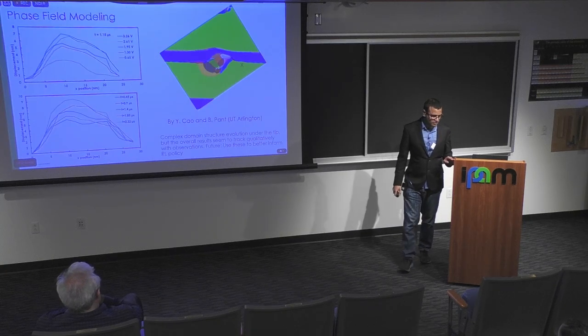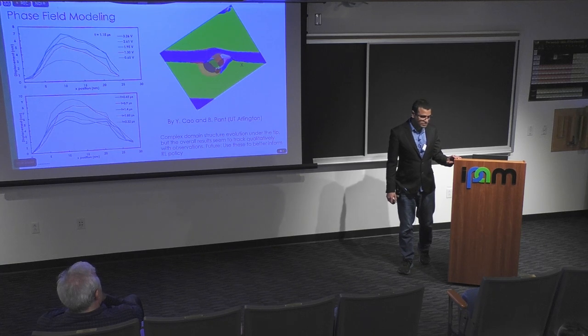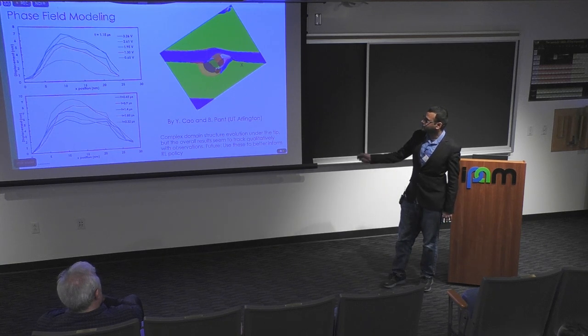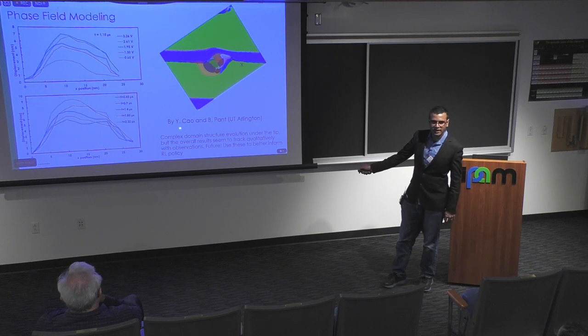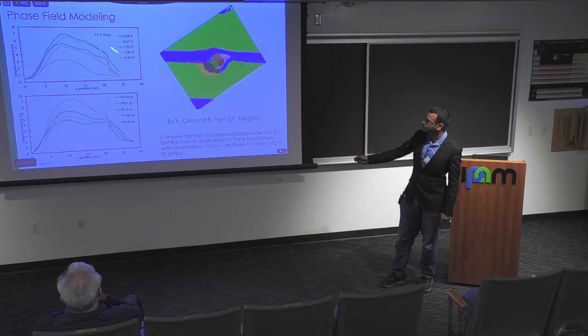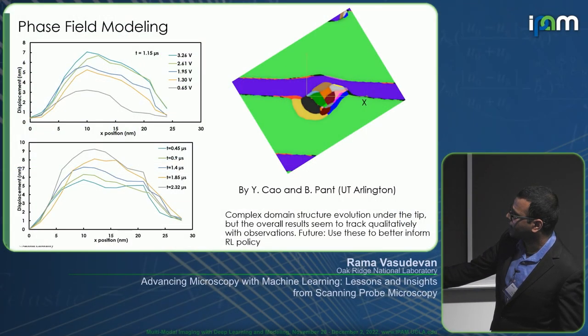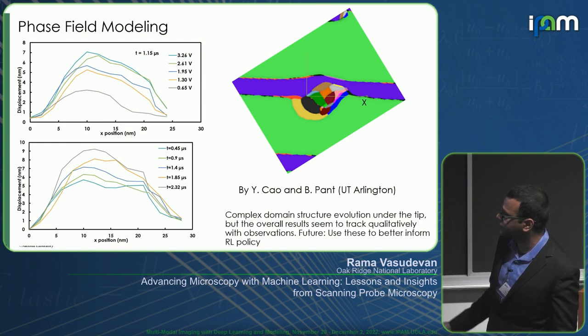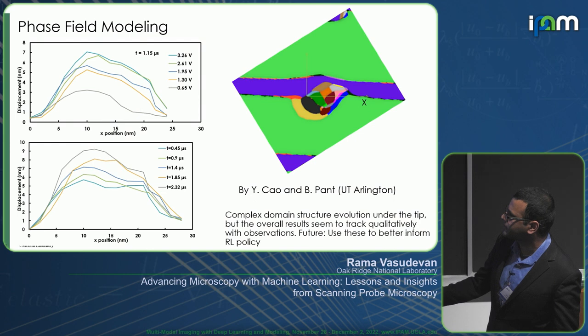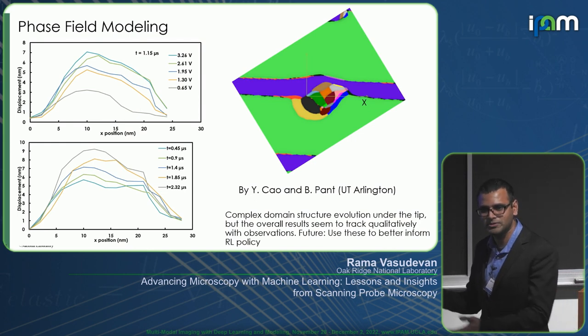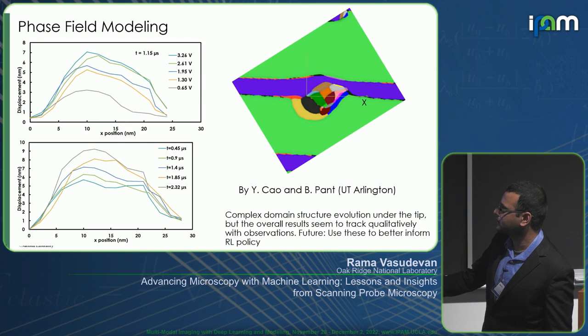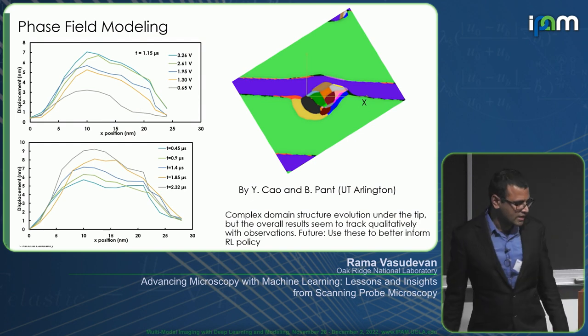And just to confirm, this is what we really think is happening. We did some phase field modeling. Actually, this is phase field modeling by Yi Cao and his student at UT Arlington. Yi Cao is a former postdoc at Oak Ridge, and he's become an associate professor at UT Arlington. And so he did some phase field modeling for this particular system. Basically, the point that I'm trying to show is that they did the same thing that we did in experiment through simulations. And you see that the results qualitatively match quite closely. You see the asymmetry here in the wall displacement as a function of position for different voltages, which is very similar to what we actually observe, which is kind of nice.